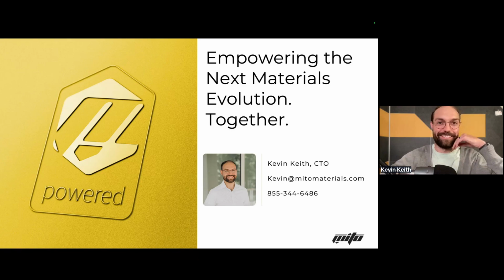With such low percentages of graphene used in these applications, how do you ensure the mixing is uniform? Yeah, so that's one of the key benefits of our functionalization, that it enables a good dispersion, but you also don't need a totally homogeneous dispersion. Whenever it comes to pure graphene materials, non-functionalized, when I say functionalized, I mean more than oxygen or amines on there. The classical ISO definition that's coming down the pipeline is that oxygen, amines, any element that's just tied on there, is not functionalized. Our chemistries allow for a lower barrier of entry where you don't have to ultrasonicate, you don't have to mix for 30 minutes, that type of thing.